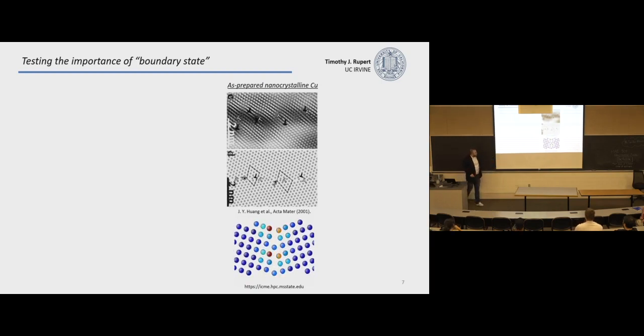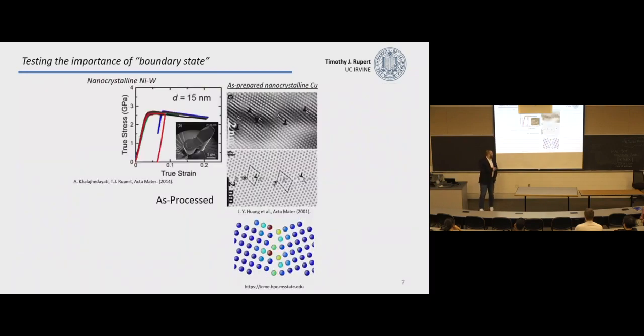This is nice because it's something you can test and poke at relatively easily. So, sorry, wrong way. We started doing this. We made electrodeposited nickel tungsten. This is in the as deposited state. We could go and test what our baseline mechanical properties are, make little micropillars, get stress strain curves. Our strength is about 2.5 gigapascals, and we can see how much we can load it up before it starts to fail. What's nice is this extra disorder is relatively easy to get rid of.